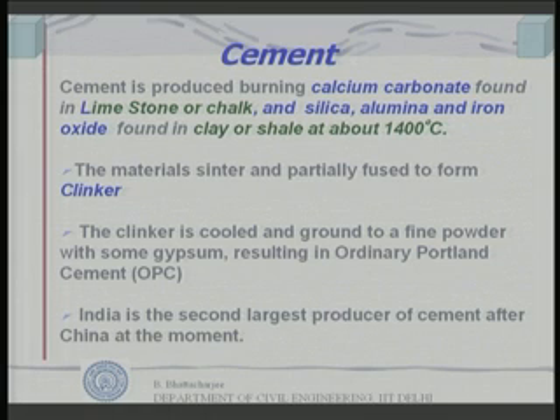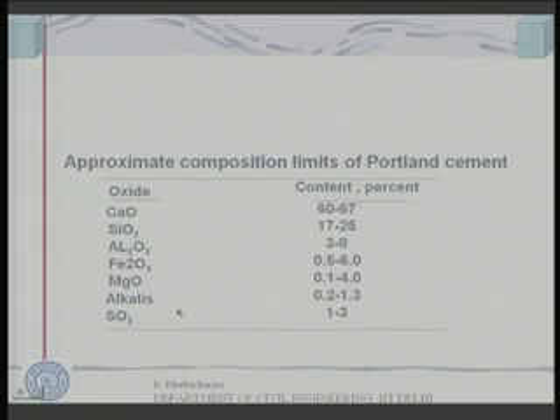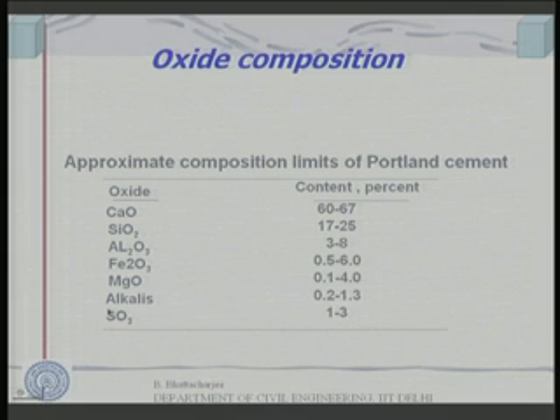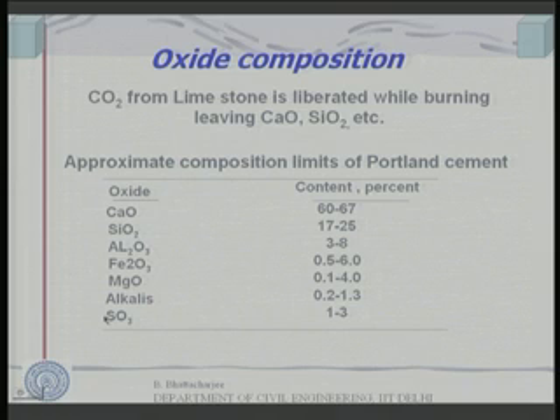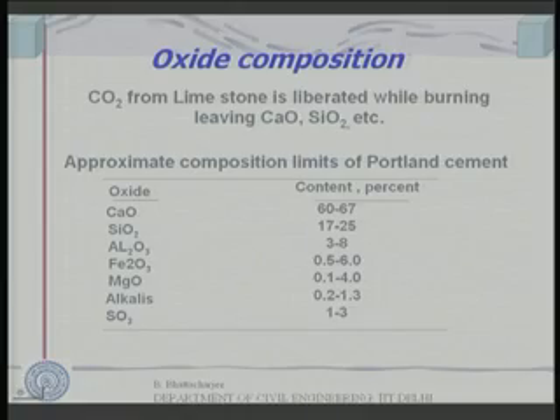Just for the sake of information, India is the second largest producer of cement after China at the moment. Now we can look into the oxide composition of the cement. You see, we burn limestone, and limestone is calcium carbonate. When you burn limestone, the carbon dioxide is liberated, leaving calcium oxide. The clay and shale leave silicon oxides, iron oxide, aluminum oxides. So, various oxides are left after burning and they form into solid solutions, and therefore cement is composed of various inorganic oxides.